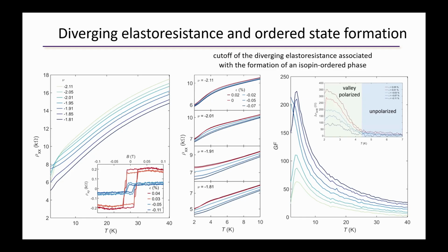Okay, so I know how to answer your first question. I think silicon famously has a very large gauge factor. I think that's also of order 100. And then some of these iron-based superconductors have gauge factors of order 100. So I would say it's comparable to or larger than other materials that have been measured before. And the way in which we extract the gauge factor is actually a lower bound, if anything, because we don't know quantitatively the precise amount of strain in the graphene. Whether it's related to some piezoelectric effect, this I don't know, and I'll have to think about more carefully.